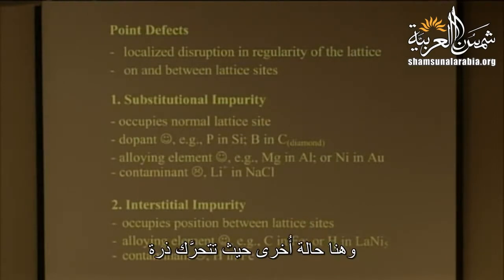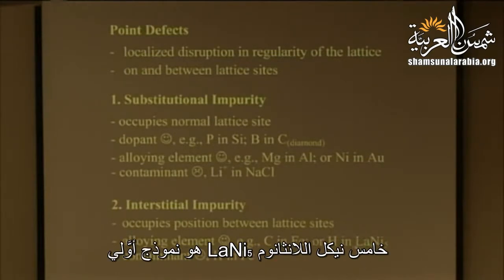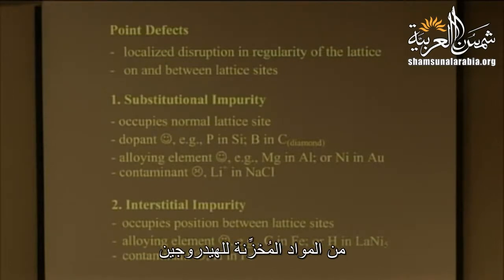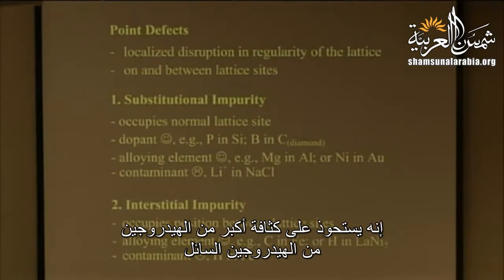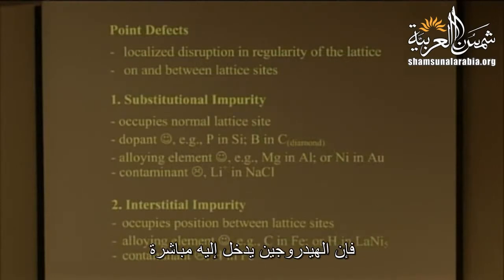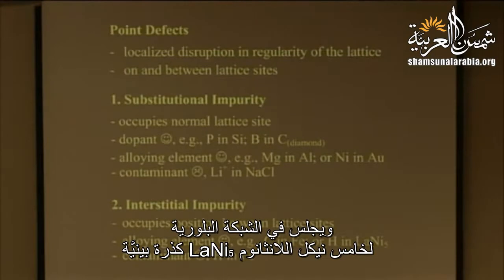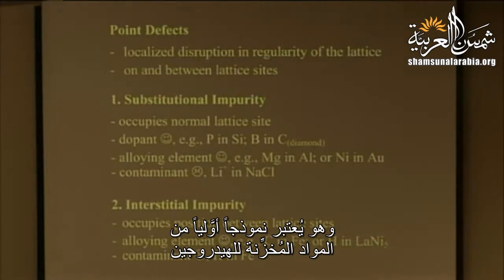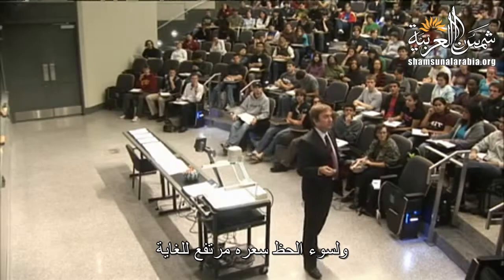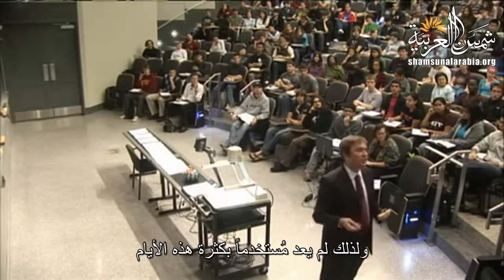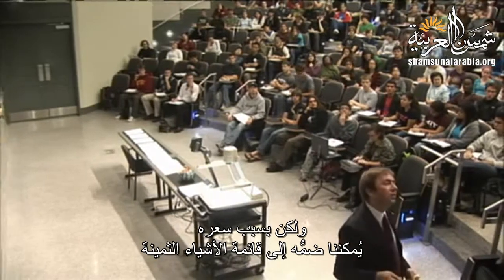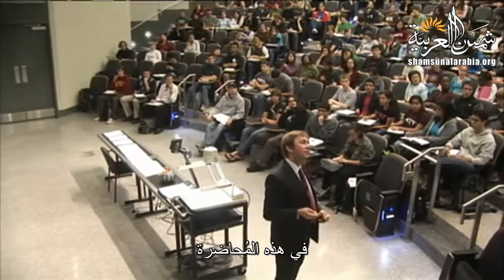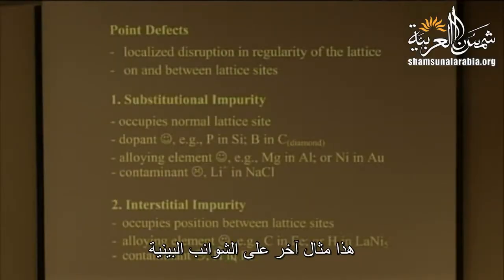Here's another example of a situation where an atom goes into a lattice and creates an interstitial impurity. So lanthanum nickel 5 is a prototype hydrogen storage material. It takes up a huge amount of hydrogen. It takes up a greater density of hydrogen than liquid hydrogen, actually. So if you expose this to hydrogen, the hydrogen just goes right in, and it sits in the lanthanum nickel 5 lattice as an interstitial atom. So this is considered to be a prototype hydrogen storage material. Unfortunately, it's extremely expensive, so it's not being used very much these days. But on the other hand, it goes well with our GEM theme in this particular lecture in terms of expensive things.